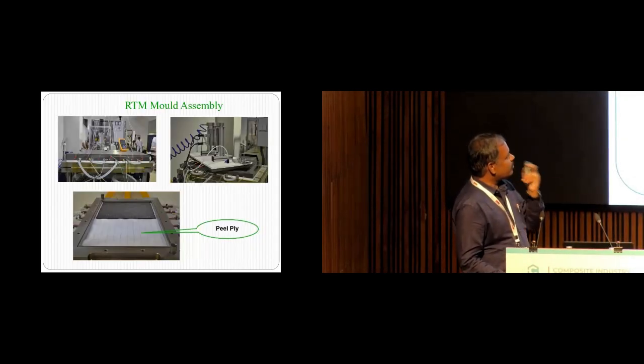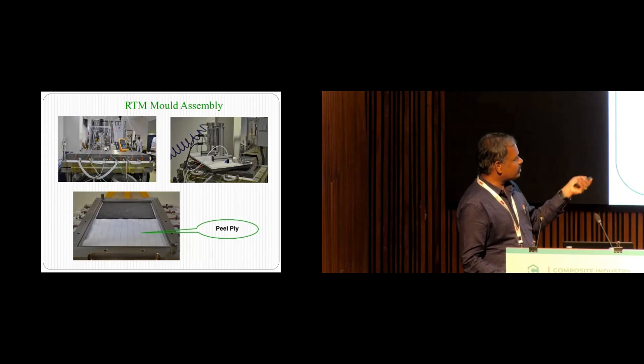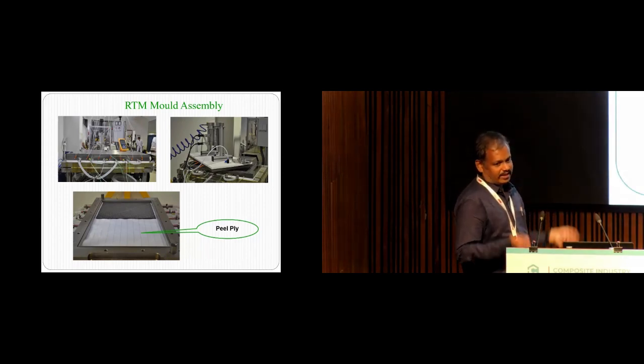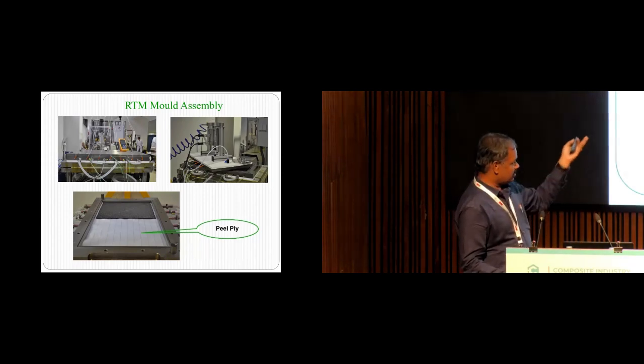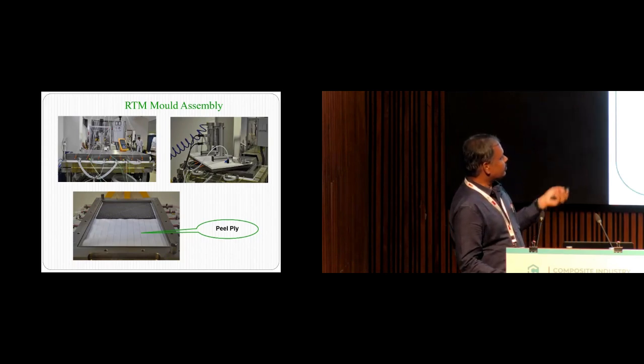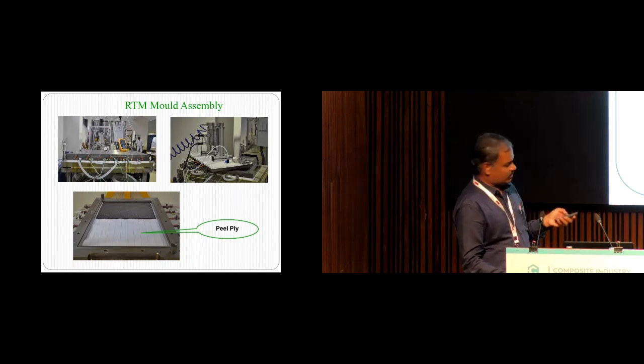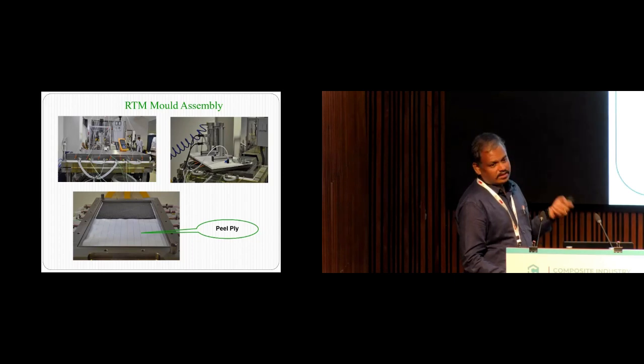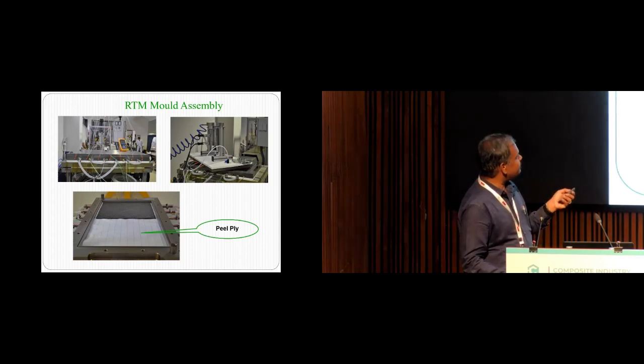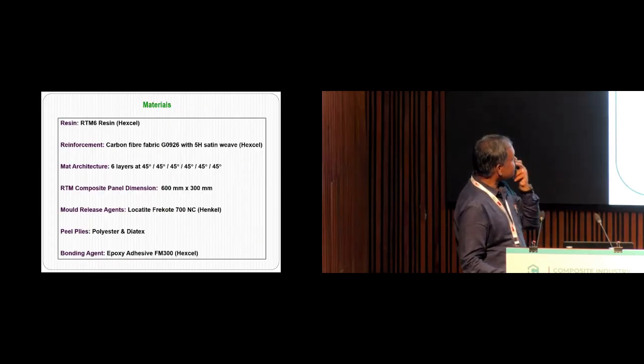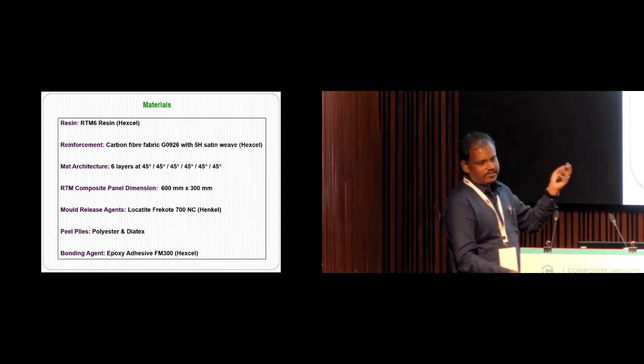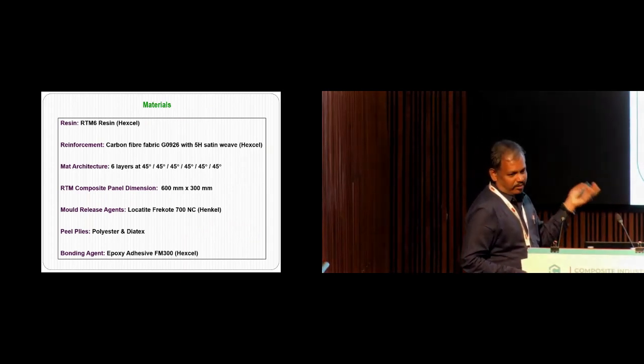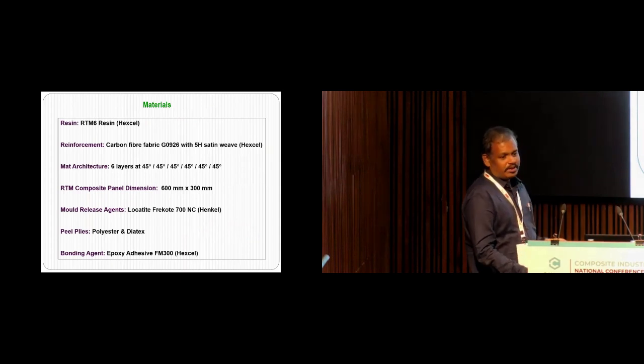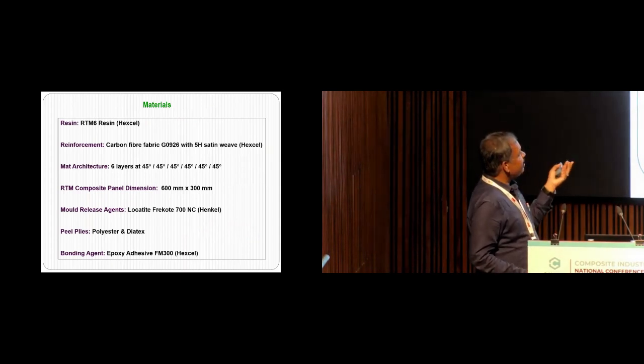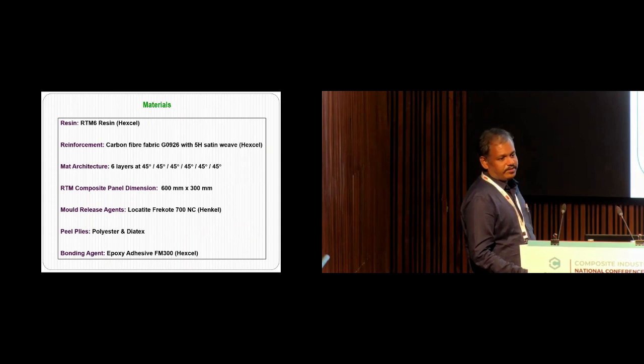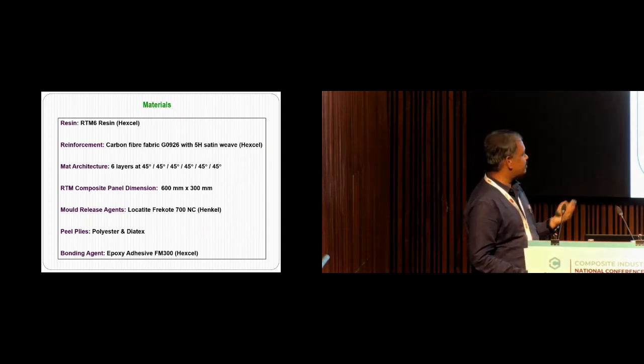So these are some of the mold parameters. Obviously, you have to use peel ply so that you can extract the panel from the mold. It is designed for 600 millimeter by 300 millimeter dimension. Again for RTM, first we checked with the hot press process, and next is the RTM process. Same material we have used, but only the dimension has been varied, 600 millimeter by 300 millimeter.